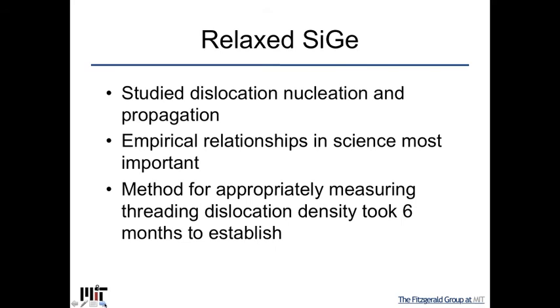An idea of how you have to understand what's going on through experiment before you can model. Measuring the threading dislocation density at low defect density in the previous view graph is actually quite a hard problem, and so we spent 6 months establishing that technique. And the reason I mention that is that in most companies today, spending 6 months to characterize a key parameter in order to make a huge advance, even though the advance could be fantastic, it's a rare organization that's going to let you spend 6 months to establish that today.